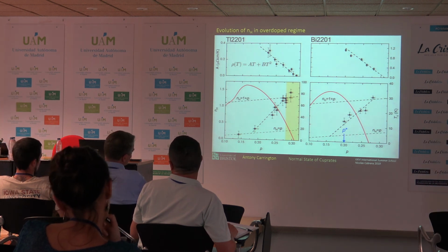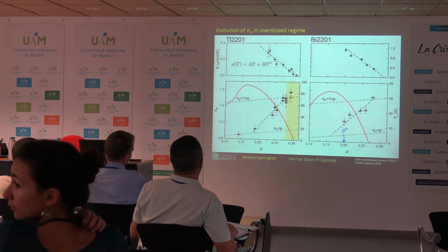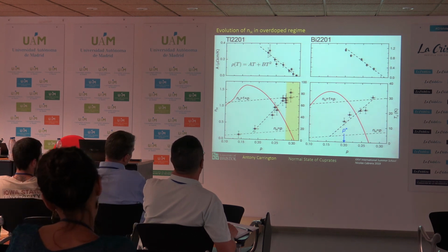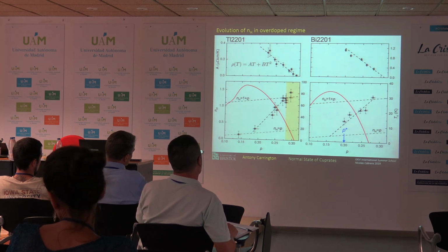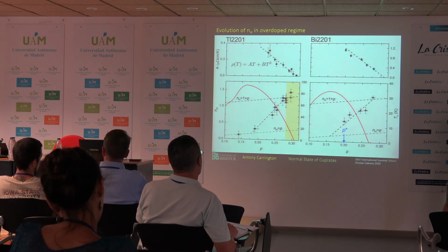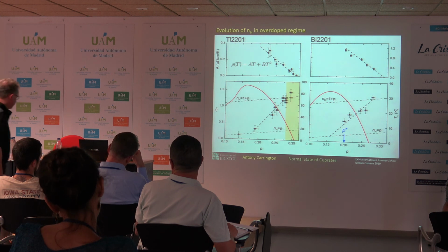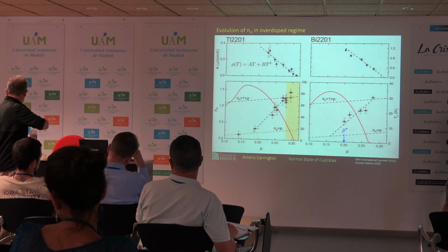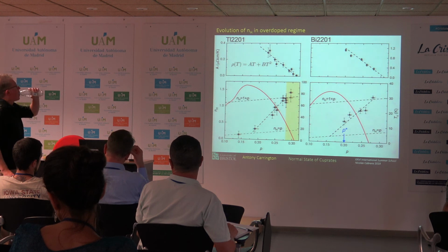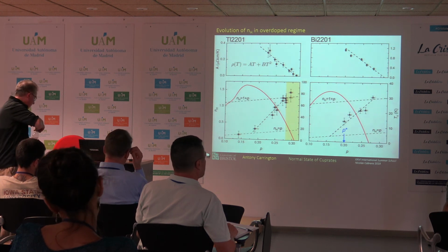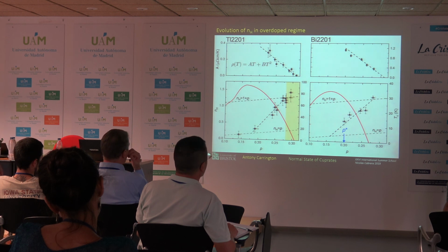If I may return to the same questions that I asked you, because you again showed this formula, just from a purely experimental perspective. I think there are two ways to interpret or fit experimental data on resistivity. One is by a single formula, which interpolates between T squared at very low temperature and then crosses over to linear in T at higher temperature, and then depending on doping, you change this crossover temperature. Or by just two independent linear in T and quadratic in T parts. Experimentally, can you distinguish between the two? No. That was a pure answer.